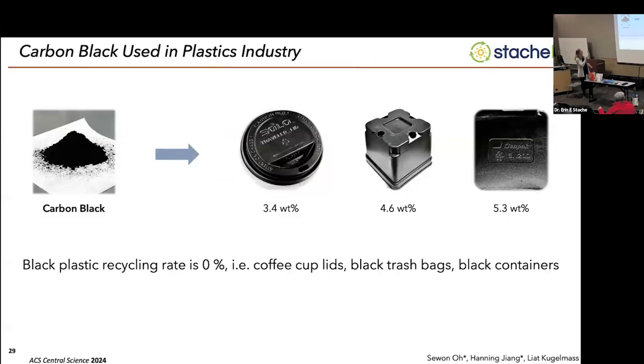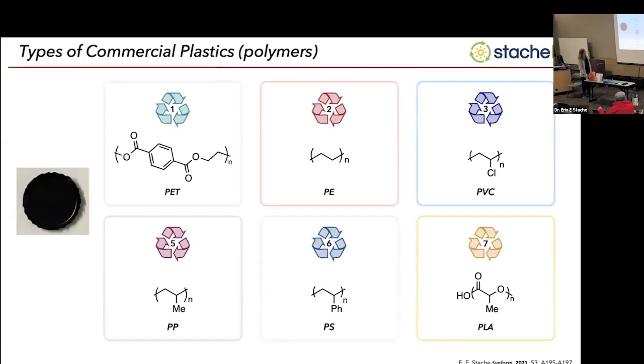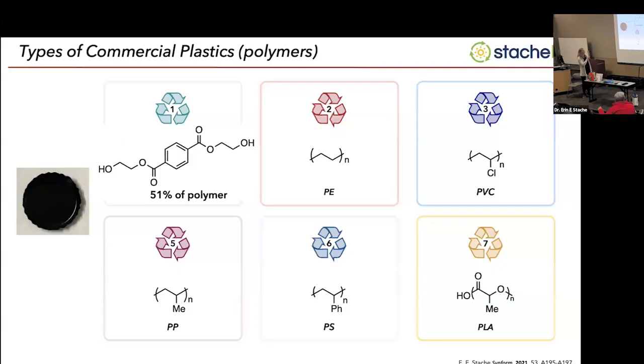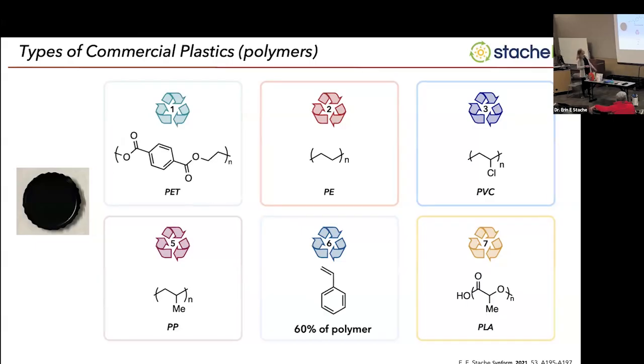We found a bunch of black plastic. Again, you can find this anywhere, right? I have a bunch of samples up here. You can find lots of other sources. About 20% of all the plastic we have contains some type of black pigment, carbon black being the cheapest. And what we found is that we could mix it in with some of these polymer resins. So we took some PET. We've actually improved this to almost quantitative yield now. So we can get essentially the monomer back from mixing this carbon black with the plastic and shining light on it. Simply light, including sunlight.